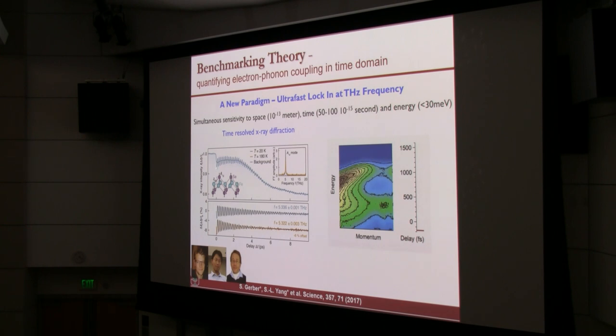And we did the diffraction experiment using coherent light sources, LCLS and SLAC. And you can see here the pump and the probe. And we were very, very lucky, okay, in the sense of there's one dominating mode you can promote in that. It turns out this was done by Raman, is the mode corresponding to that interesting selenium atoms moving up and down. Okay, in this case, they can be coherently excited, and you can see the oscillation.